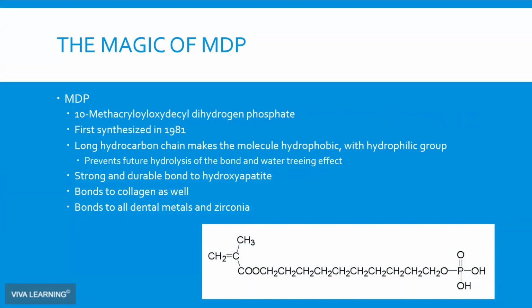So this functional monomer was first synthesized in 1981. It first hit the market, I believe, in the form of Kuraray's Panavia line of products. But what was interesting was this long hydrocarbon chain, this 10-carbon chain, which was very hydrophobic. That wasn't fully appreciated until more research was done later by others, which showed that this hydrophobicity helped to prevent hydrolysis of the bond between tooth structure and the adhesive. The consequence of preventing this hydrolysis is that the bond is durable and strong, at least to tooth structure.